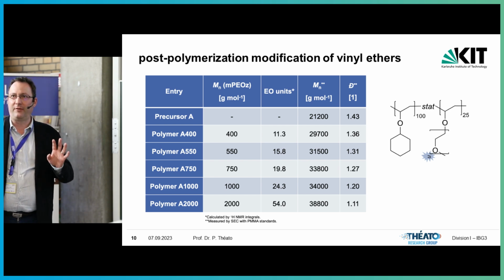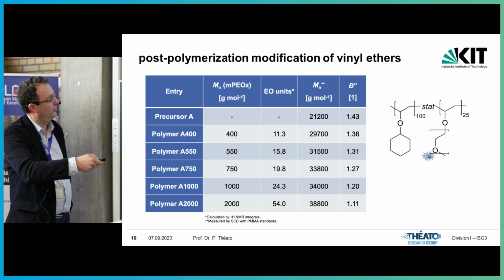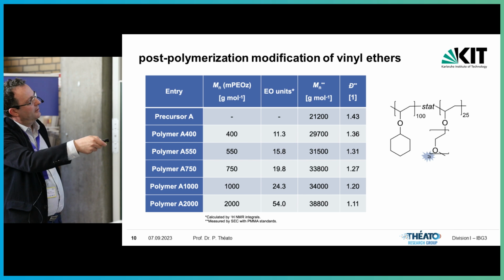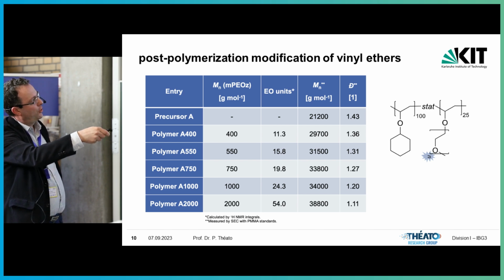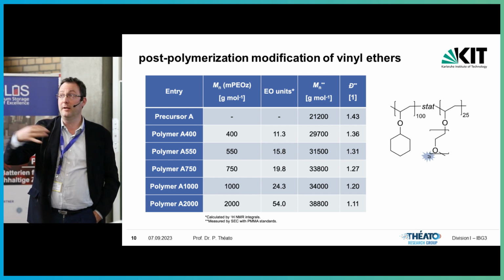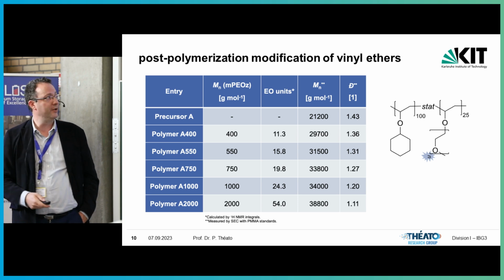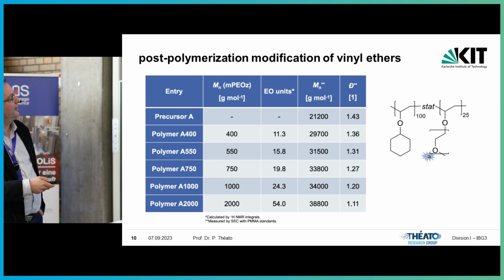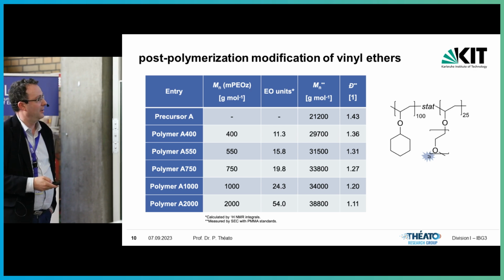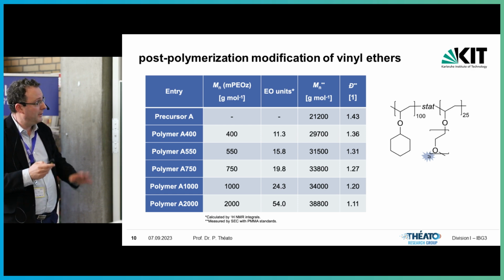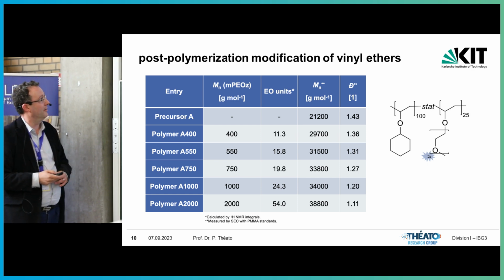So for the non-chemist, I apologize for these structural details. But essentially, the protons from that reactive unit here, the tosyl part, the aromatic units, show up here. And after the conversion, they completely disappeared. Okay, this is an indication that we get a quantitative conversion to really have a system that is in there. And molecular weights still stay pretty fine. You get an increase in molecular weight as we want, but not really necessarily a broadening of the chain. So we really have a system in hand that looks quite nice.